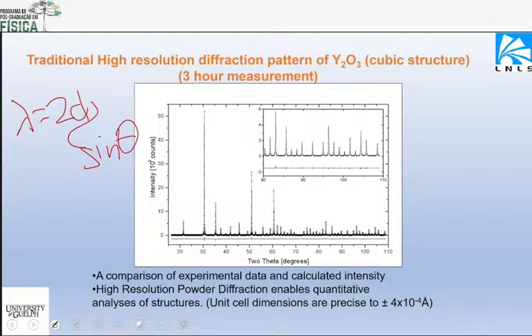Every single set of planes in a crystal is going to create a Bragg peak. These Bragg peaks are very, very sharp, and so you can measure their angle very carefully. And if you know the wavelength and you measure the angle carefully, you can figure out the d-spacing, the spacing between the planes. And the intensity of the peaks tells you where the atoms are in these building blocks, the unit cell. So this is yttrium oxide.